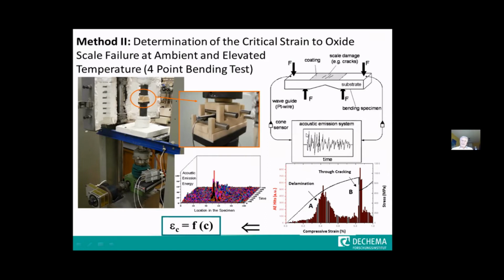Especially with modern electronic equipment, it's very easily possible, as you see down here, to locate the position of the signal. And of course, you can also make an analysis of the type of the signal, of the energy, of all the information that is contained in the acoustic signal in this test. And you can do it, of course, if you have, again, platinum waveguides here. You can do it like shown here with a furnace. So you have the 4-point bending equipment in here.